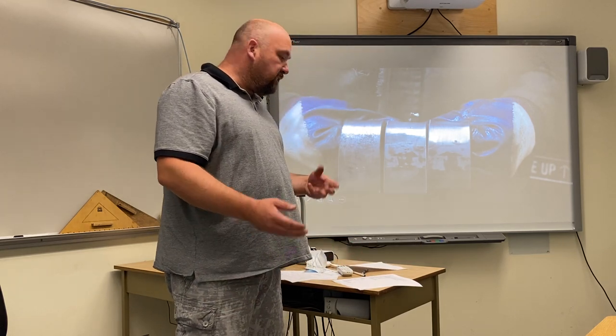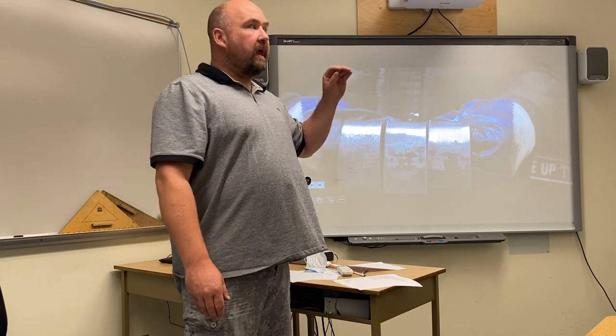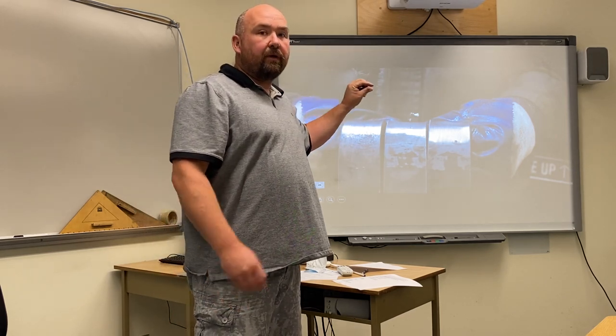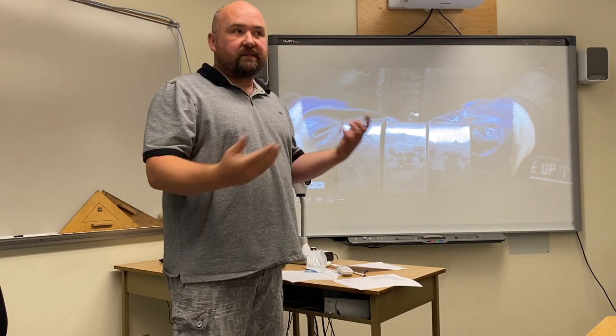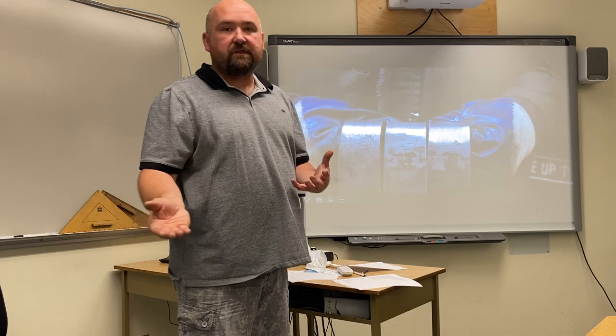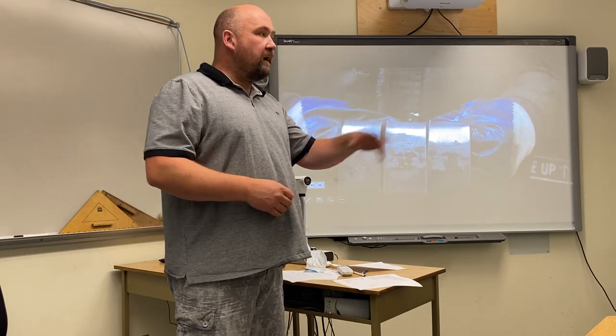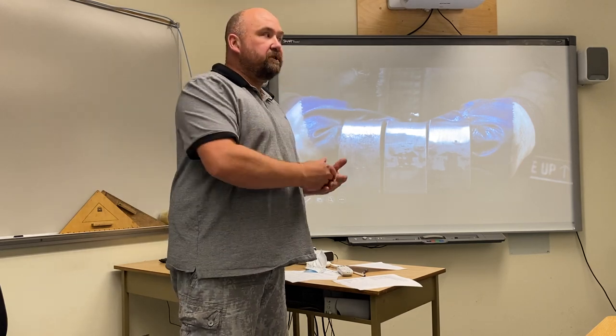The leg length of your fillet must not vary more than 1/16 of an inch in size from one end of your plate to the other end of your plate. So you can't go from having a 1/4 inch fillet on one end to a 1/8 fillet on the other end. That's classified as a failure and you failed your visual inspection before you even continued the test. So you're going to throw that plate away, you're going to pay the inspector another $150 and he's going to issue another set of plates and you're going to start over again.